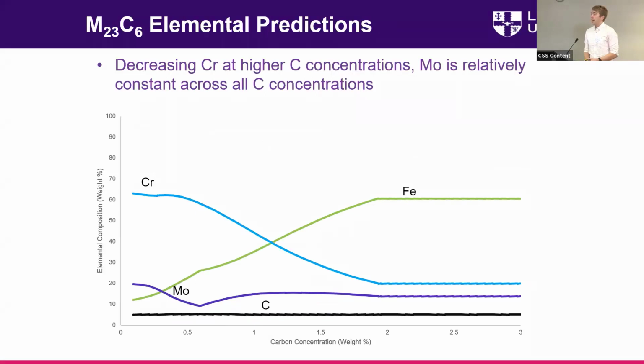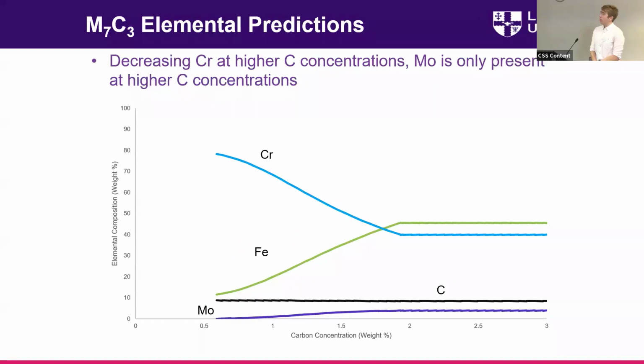So if we have a quick look at the elemental predictions for what these carbides would consist of, for the M23C6, we can see that at the lower carbon concentrations within the substrate, chromium and molybdenum with a small amount of iron are predicted to be present, and at higher carbon concentrations, the ratio between the iron and the chromium is predicted to switch over, so with higher iron and lower chromium, but the molybdenum remains relatively consistent. And if we do the same for the M7C3 carbides, they're not predicted to form until a slightly higher carbon concentration within the substrate, but you have a similar kind of pattern with the chromium. So at higher carbon concentration, you have more iron relative to the chromium. But the main difference between the M7C3 and the M23C6 compositions is that the molybdenum is predicted to be a lot lower in the M7C3 carbides.